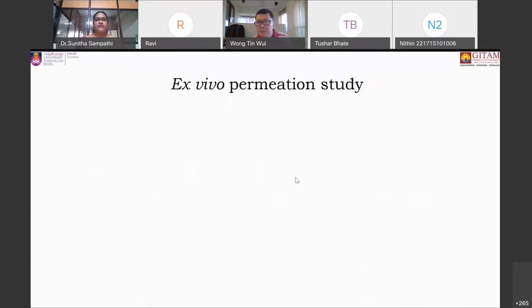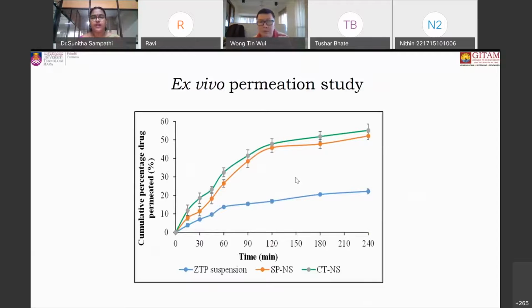Now, later we conducted ex vivo permeability studies using the nasal mucosa of the pork. So you can see from the graph that in the case of the plain drug, less than 20% of the drug was permeated. But if you look at the permeability coefficient, when it was calculated, it was very high for the nanosuspension prepared by the combination technique. It was 0.4489, many folds high as compared to the plain drug, which was only 0.1.